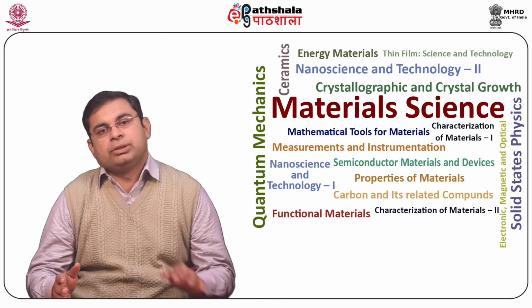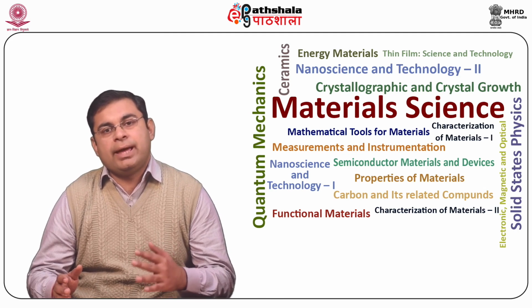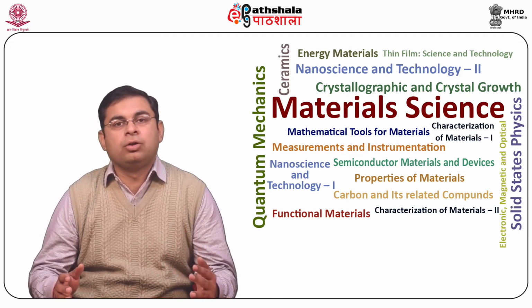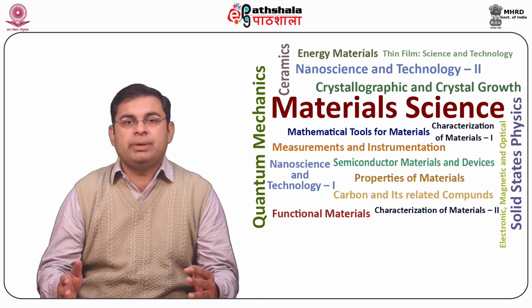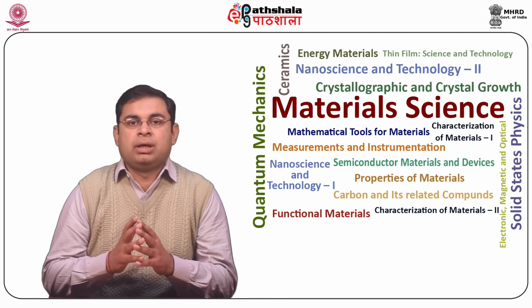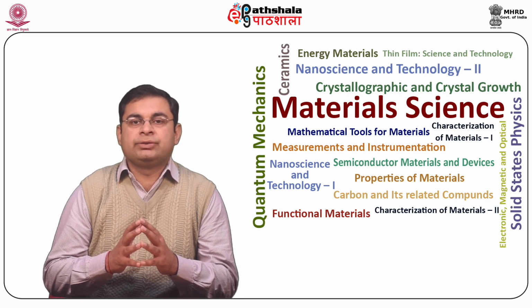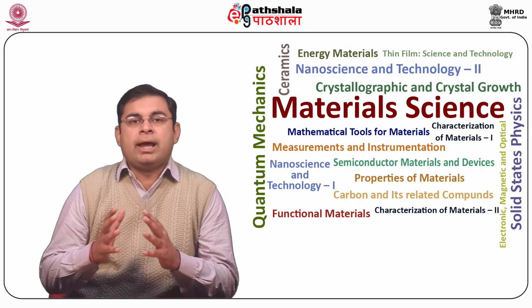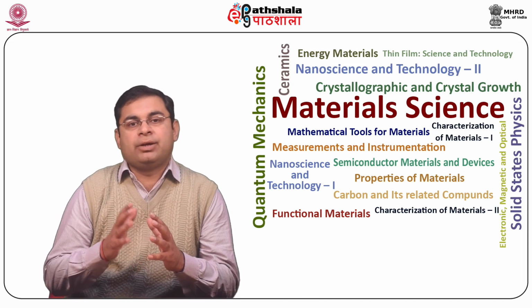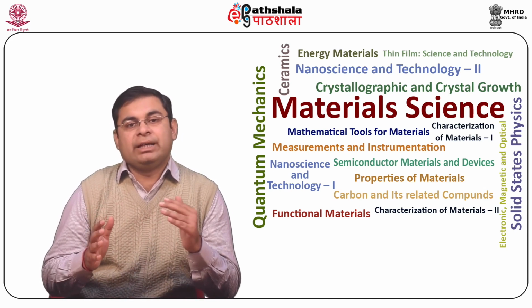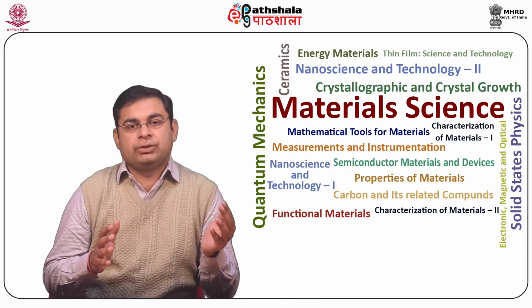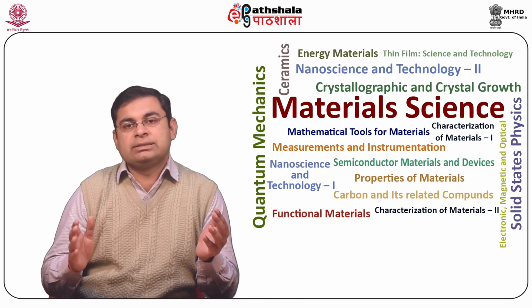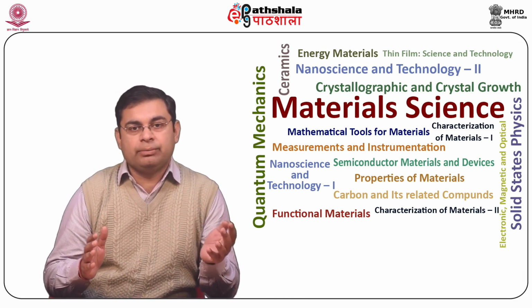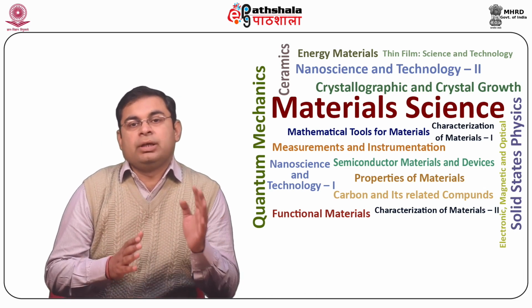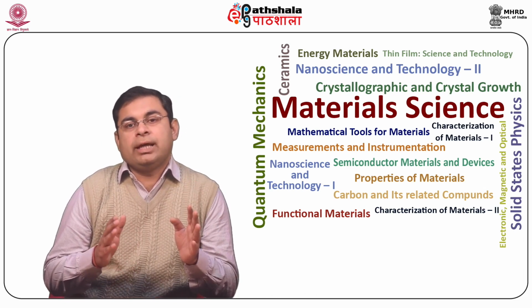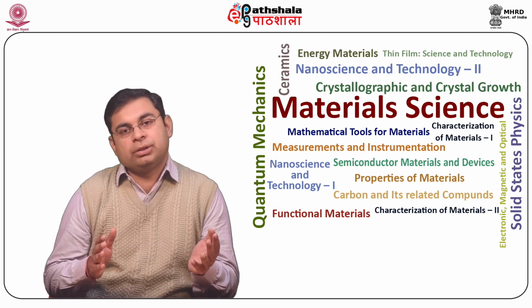In the case of metals, the density of charge carriers as well as the sign of the Hall coefficient depends upon the energy band structure of the metals. Alkali metals, that is lithium, sodium, etc., and transition metals like copper, silver, etc., have negative electron charge carriers with a charge carrier density of 1 electron per atom. In this case, equation 6 can be used to obtain the Hall coefficient.